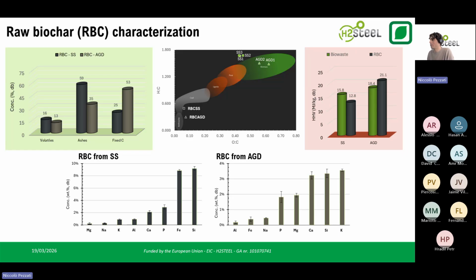Whereas it is relevant to notice that when treating the sewage sludge, the caloric density, so the higher heating value, decreases. And this is because of the high ash content in the sewage sludge, which creates a dilution effect despite fixing the carbon matrix in the substrate.